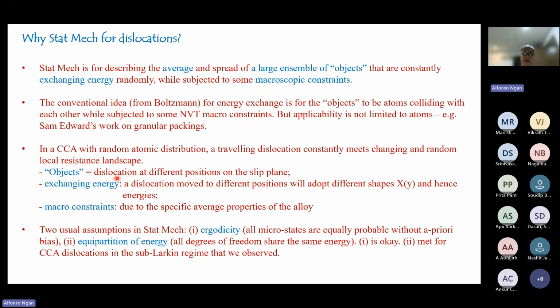Because of the fluctuating atomic environment in a CCA, the dislocation will be interacting with that fluctuating environment. So the so-called exchanging energy would be manifested by that stochastic interaction. The macro constraints, which are also important in StatMech consideration, will be due to the specific average properties of the alloy. So usually in StatMech, we have 2 requirements. One is ergodicity, which requires that all microstates are equally probable. That should be okay, right? Because there is no particular reason why a certain state is more probable than another, even for a dislocation moving to different locations of the slip plane.